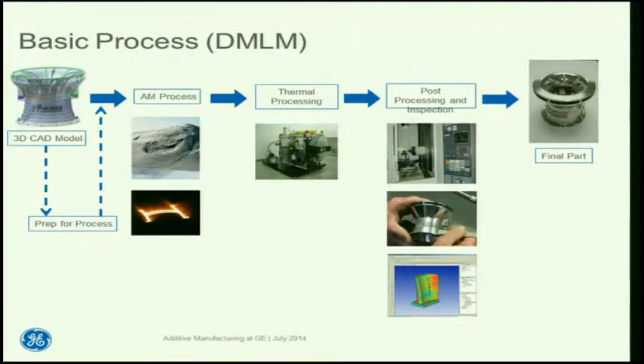And once that part has been completed and built, we then pull it out of the machine. We typically go through a post-thermal processing, so a stress-relieving operation, typically HIP, solution heat treat, that type of thing. Once it's through the thermal processing, we then pull the parts back. We typically, again, will have some kind of post-machining in order to have good fit-up capability and tolerances in certain areas. We might hand bench the parts to get a better surface finish. Then we inspect, and then we can ship the parts. Depending on the complexity, the parts can be large, they can be small, they can be complex, typically complex and typically small right now given the state of the industry. But once that's done, we're able to ship parts within perhaps a couple days up to, say, a couple of weeks.